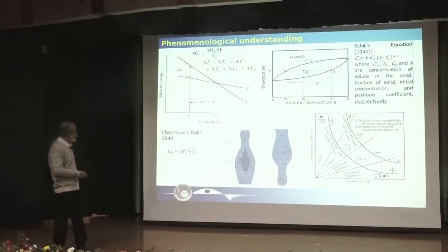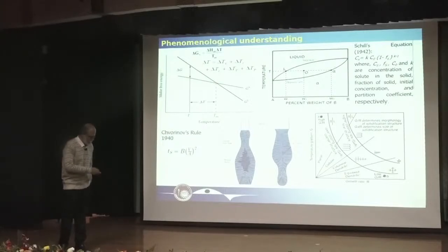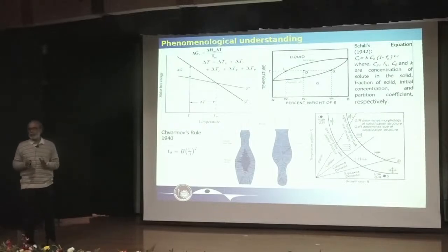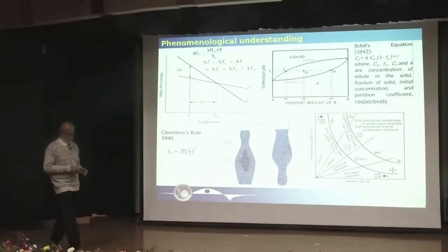So for that, they identified two parameters, that is temperature gradient and growth rate, which you can measure. And as a function of this, they could map the different kinds of morphology, starting from planar to cellular to columnar dendritic to equiaxed dendritic. So that shows under which condition which kind of morphology selection is possible. And second thing, it is expressed in terms of G by R ratio and G into R, that is in this direction, which shows the tendency of refinement of grain. If you follow this direction, dendrites gradually become finer and finer. So that's how an empirical foundation for the solidification process was established.